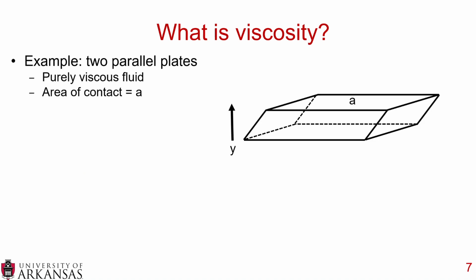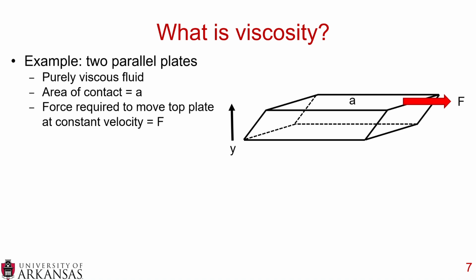Now with viscosity, the easiest way that I have found to qualify viscosity is to pretend you have two parallel plates, and between those two parallel plates you have a purely viscous fluid. The parallel plates have an area of small a, and you apply a force so that the top plate moves at a constant velocity. That velocity can be represented here: the velocity is 0 at the bottom and at the maximum at the top, and you can see this is a linear relationship in this viscous fluid.